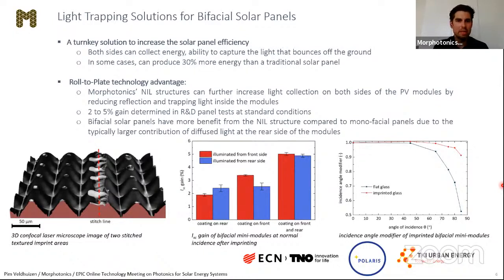So what we can do is imprint a microtexture or a nanotexture. In this case, it's a microtexture on the exterior of the bifacial solar module. And this makes sure that there is light trapping and less reflection. The light trapping ensures that the light does not exit the module anymore, but is absorbed more efficiently than if you have no coating or no texture. And on the bottom left, you can see an example of how the texture looks in 3D.